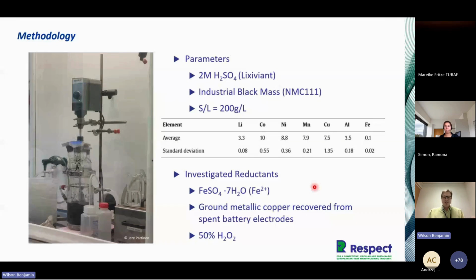We had a nice highlight there from Joanna talking about the use of peroxide. But peroxide itself can be quite expensive and has a well-known high carbon footprint associated with its manufacturing process. So we tried to look at alternative reductants, in this case iron sulfate, but also copper that's recovered from the battery electrodes, and also trying to exploit some of these materials, the copper, aluminium and iron, which are already within the black mass, so we don't have to add so much reductive material.